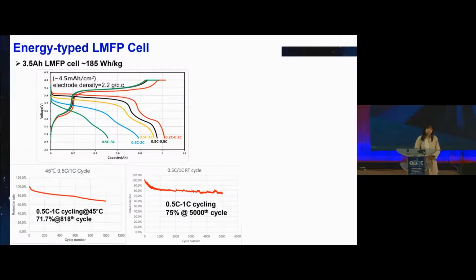We also successfully developed the so-called energy type LMFP cell with a single side electrode loading of 4.5 milliamp hour per centimeter square. With this loading, the thickness of the electrode was about 240 micron before calendaring. You can see that the electrode density was about 2.2 gram per cc. The cell also has an energy density of about 185 watt-hour per kilogram. The cell retained about 75% of the capacity after 5,000 cycles at 0.5C charge and 1C discharge at room temperature. And it also retained about 72% of the capacity after 818 cycles at 45 degrees C.